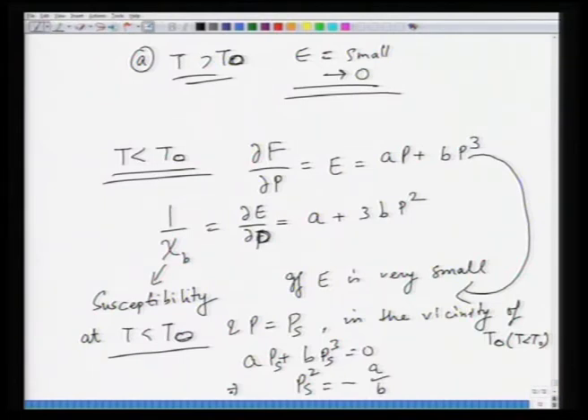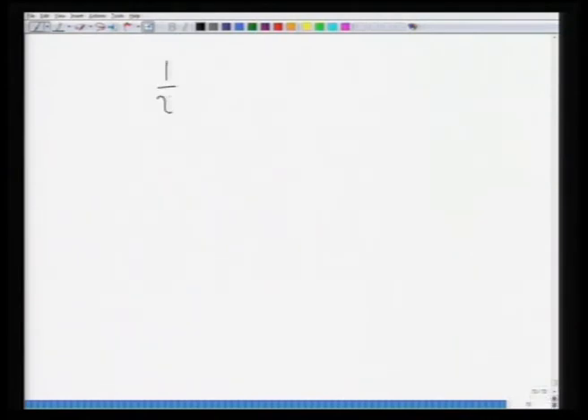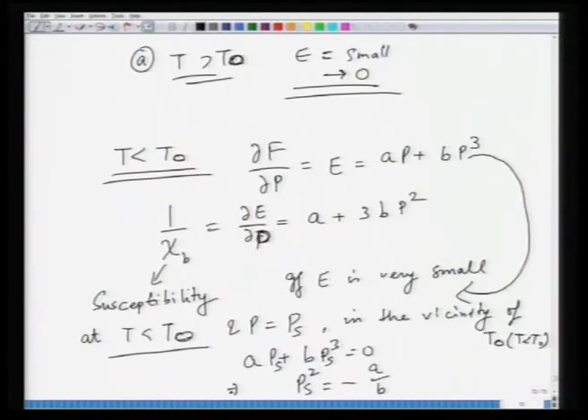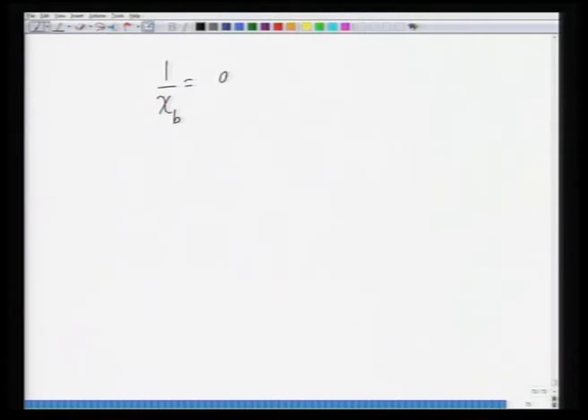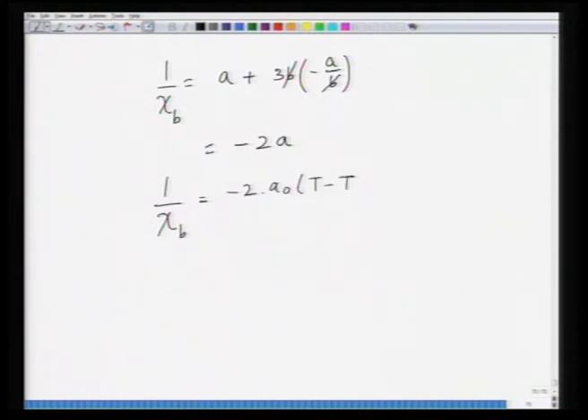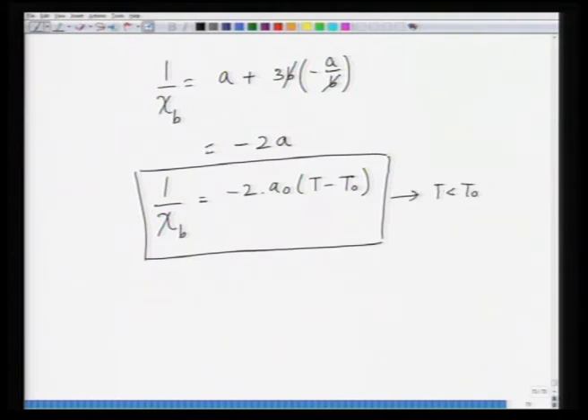Now what you do is replace this in the above equation. So 1 over chi B becomes - the expression was A plus 3B multiplied by minus of A by B, so B cancels and this becomes minus of 2A. So 1 over chi B now becomes minus 2, and A naught into T minus T naught, and this is for T less than T naught, so of course it would be positive because T is less than T naught. So minus minus will cancel each other, and since A naught is a positive quantity anyway, this would remain positive. So this is the magnitude of chi at temperatures T less than T naught.